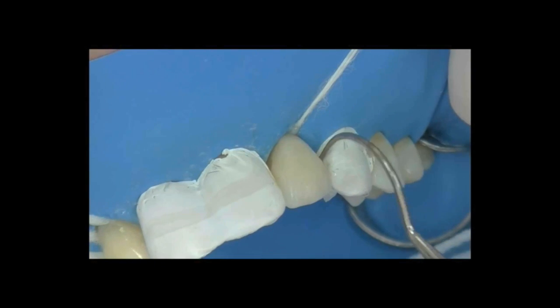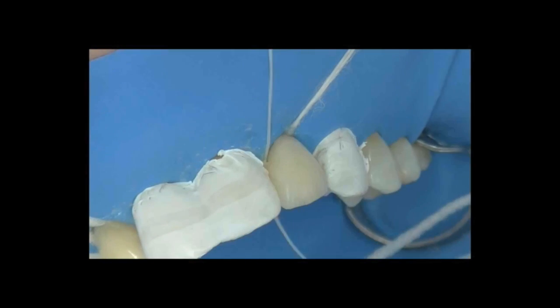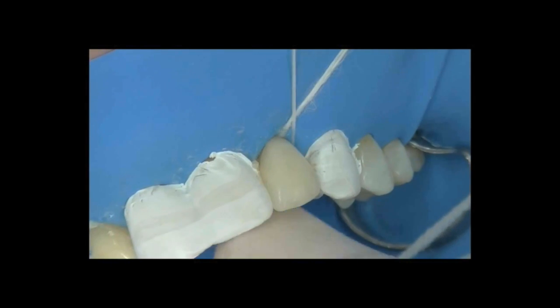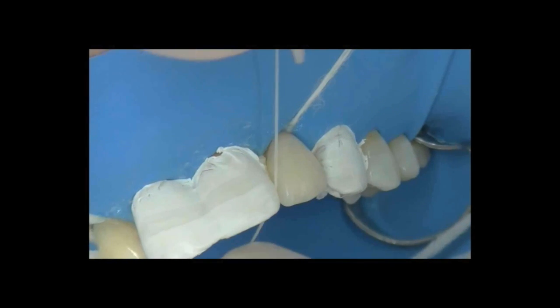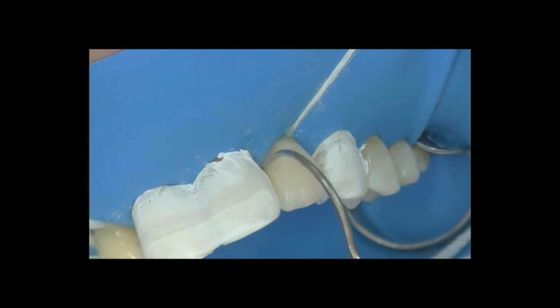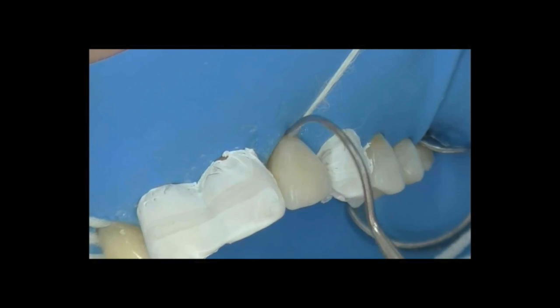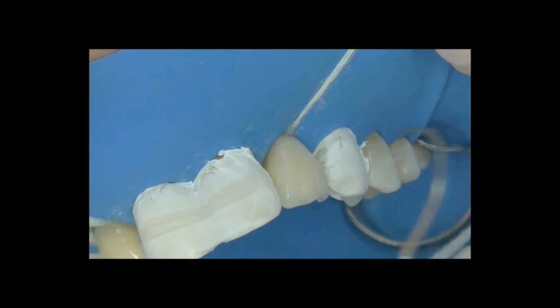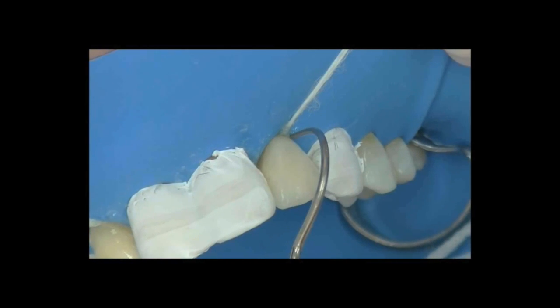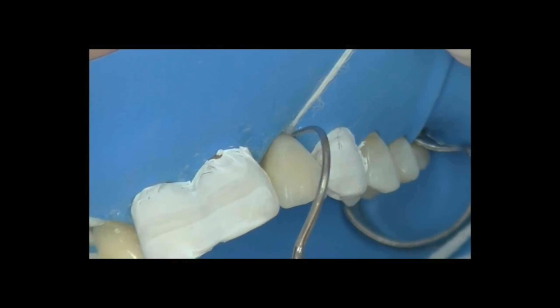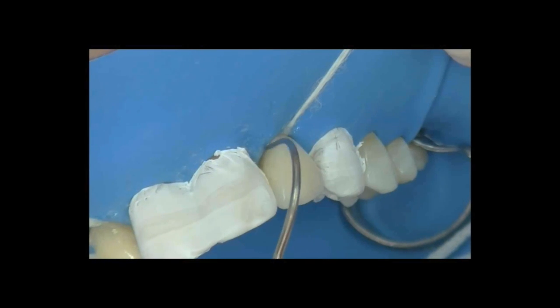So same procedure again on the other side. On the distal aspect, and then I still don't know if the positioning is okay. Do you see? This is a little bit risky. I'm maybe a little bit optimistic in that case, but it sticks so much at that stage that you can even floss in between the teeth without any risk of making the veneer move. So you see, I just push like crazy once again. It's a feldspathic veneer, about 0.5 thickness, so it's not that resistant, but there's no problem. You can just push as strong as you want, more or less.